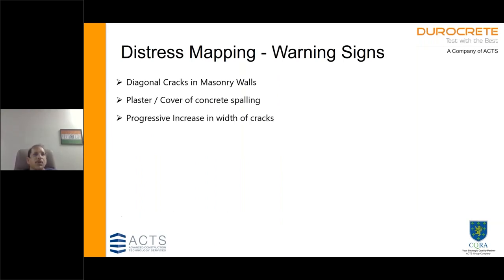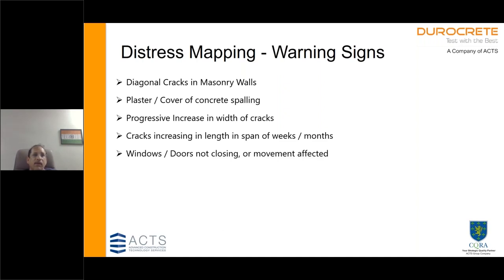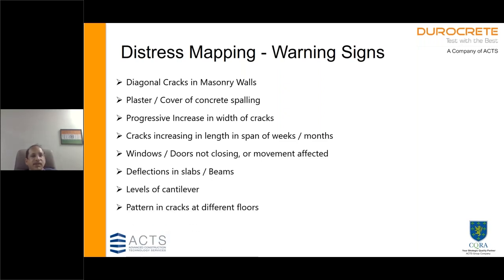So what is distress mapping? How do you do the visual inspection? Basically, we check for cracks, signs of concrete or cover coming out, and progressive increase in width of cracks. You have to track and monitor whether the length of the cracks is increasing over weeks or months. Sometimes, when the structure is really under distress, especially due to settlements, you will have windows and doors not closing, movement affected, deflections, and changes in levels of cantilevers. If there is an identical pattern of cracks on different floors, again, it is an indication of serious distress.